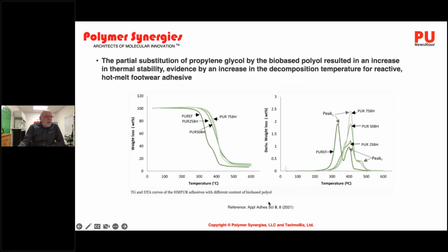Here's an example which comes from this reference in Applied Adhesive Science, where there's a partial substitution of propylene glycol by a bio-based polyol. And there are various bio-based polyols that are being used here. What we're looking at here is the thermogravimetric analysis. You can see that the polyurethane reference is this first line here. And all of these bio-based polyols provide greater thermal stability, as shown by thermogravimetric analysis. So that's an important aspect when you're formulating and designing. What environment is your adhesive going to be used in? And can I increase the thermal stability of the adhesive? This is one way that it can be done, by using these types of bio-based polyols that are referenced here in this reference.